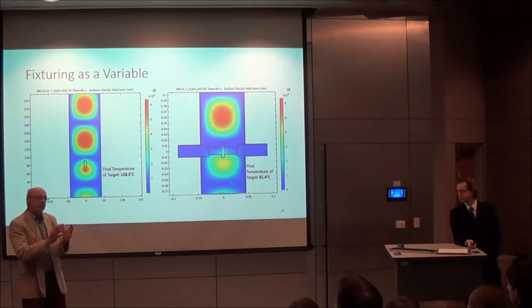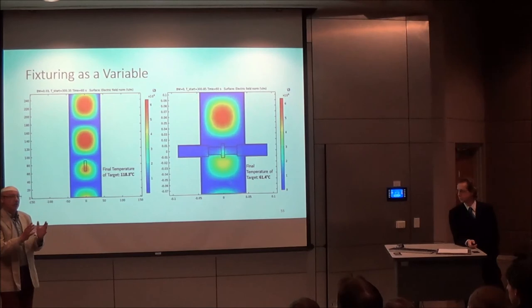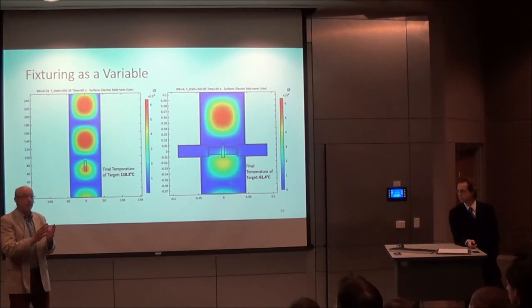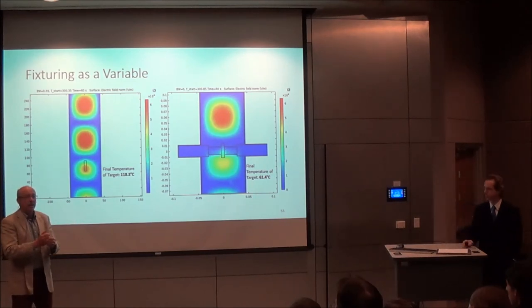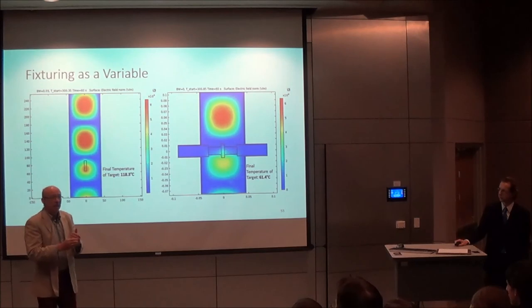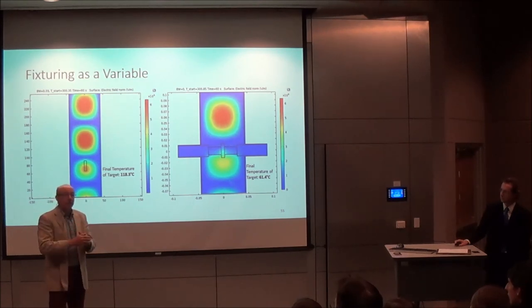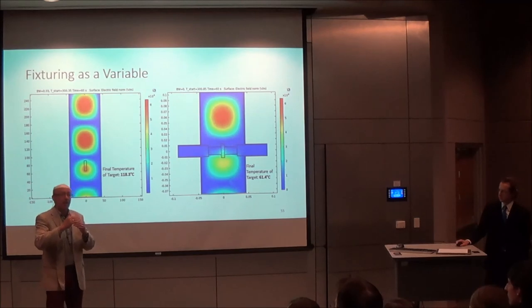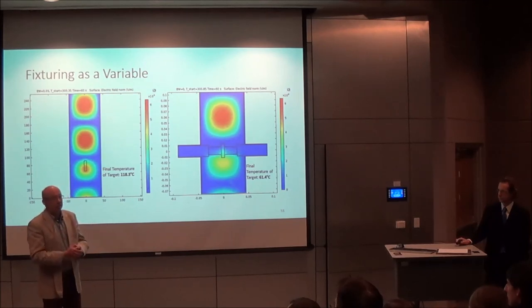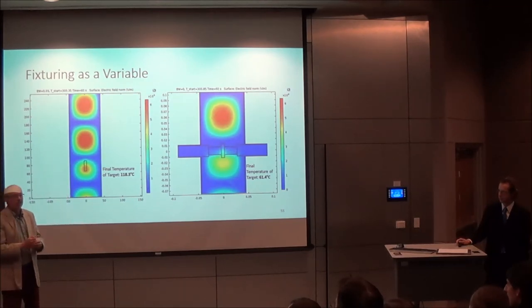Well, maybe you want to comment on the fact that lead telluride is designed as a thermoelectric to have very low thermal conductivity. So today they furnace braze them in 90 minutes because they are trying to avoid that thermal shock that would actually cause that. So microwave heating in a few minutes beats that, not necessarily from a productivity standpoint, but 4 years ago when we presented this work in Dallas to II-VI Foundation, they wanted to buy our prototype because there was no diffusion layer already formed during those 90 minutes. It's just a clear boundary. And that basically is already half of the life of a thermoelectric because during soldering, it already destroys it with the brittle intermetallics. So that really is a huge advantage to internal heating in addition to CTE expansion.